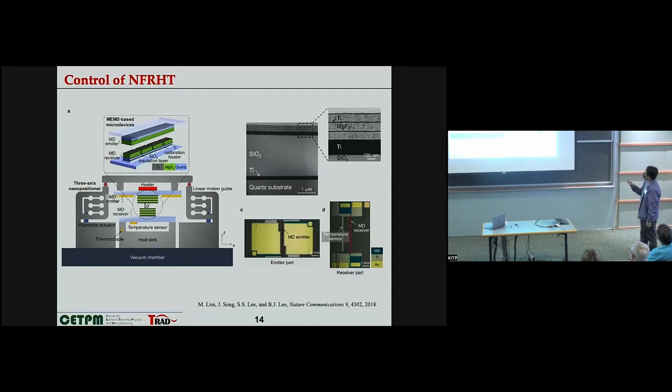We choose MgF2 as the dielectric. MgF2 has a strong phonon absorption band and supports surface phonon polaritons, and it is well known that MgF2 has very high near-field thermal radiation. But for our design, MgF2 did not play the role of an emitter. It simply acts as a dielectric spacer for these metal layers, so that it supports multiple surface plasmonic resonances.